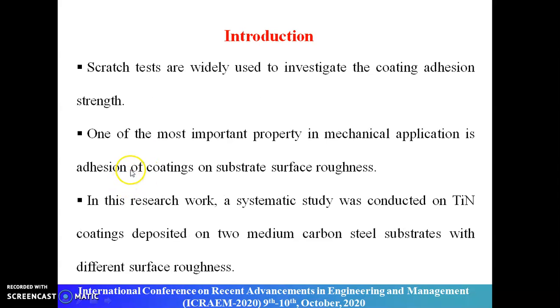Moving to the next slide, scratch tests are widely used to investigate the coating adhesion strength. In this research work, a systematic study was conducted on titanium nitride coatings on EN8 material. The effect of substrate surface roughness and thickness of the coatings on deposition of titanium nitride on EN8 substrate has been investigated through experiments with the help of a scratch tester. Investigations were carried out using titanium nitride coatings of 1.5, 3 and 5 micrometer thickness and three different surface roughness values of 0.02, 0.15 and 0.35 micrometer.